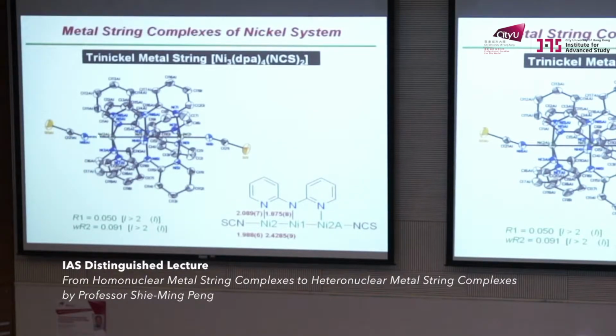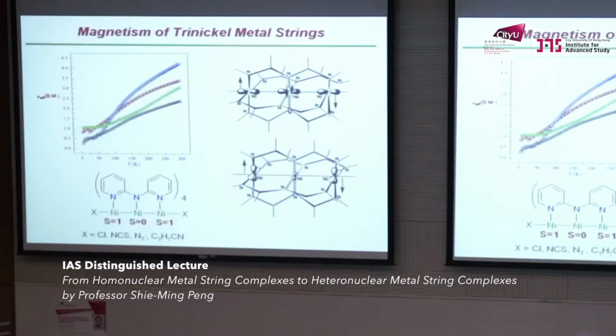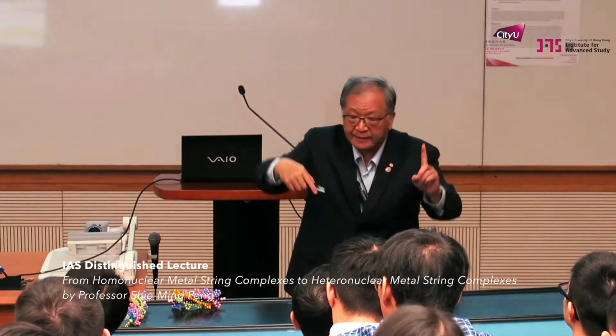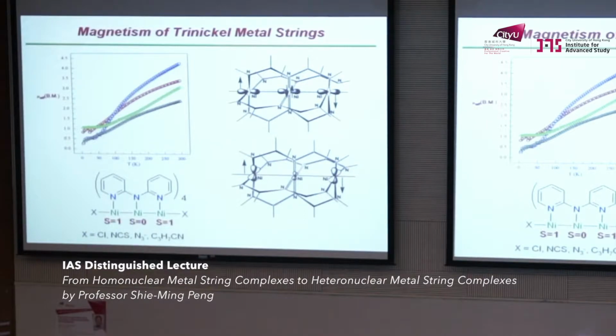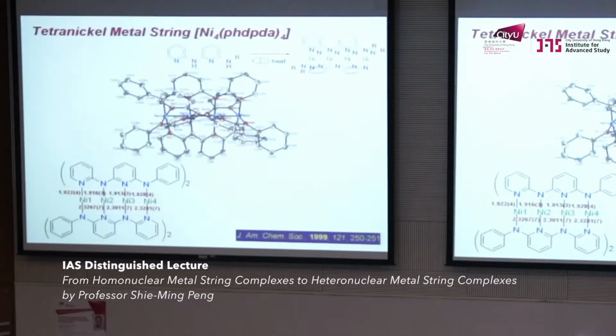So what's the electronic structure of this trinickel? From structural analysis, the terminal nickel has a long nickel-nitrogen distance, showing it is high spin nickel 2. And the inner nickel-nitrogen has a short nickel-nitrogen distance, 1.88, showing this is diamagnetic nickel 2. Okay, so spin state, there's no bond, 3 nickel 2 with the spin state 1, 0, 1. And this 1 and 1 show strong antiferromagnetic coupling. And these 2 unpaired electrons, one is located at the dz squared, one is located at dx squared minus y squared. So the mechanism will be through different pathways. So this is one pathway, this is another pathway, contributing to the antiferromagnetic coupling.